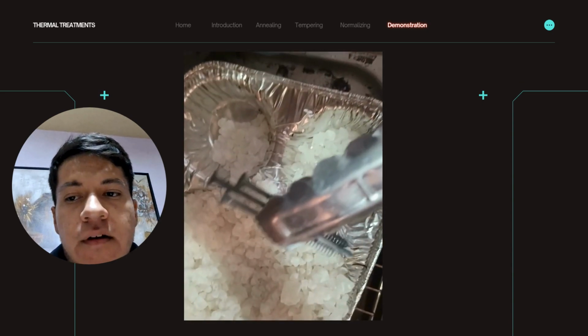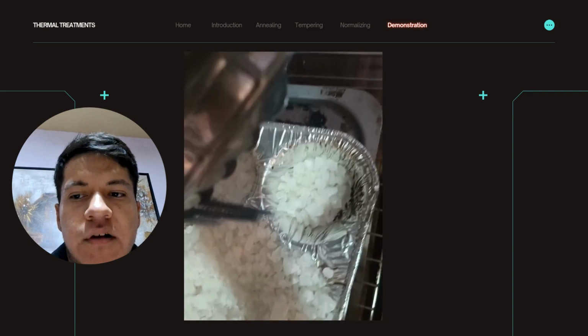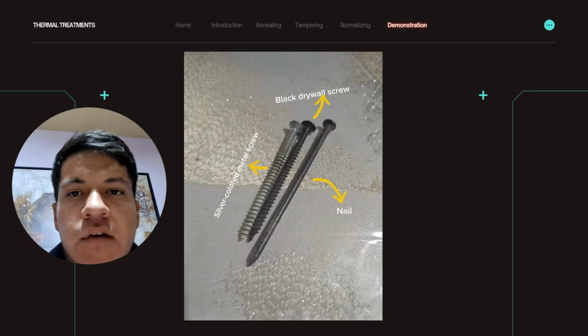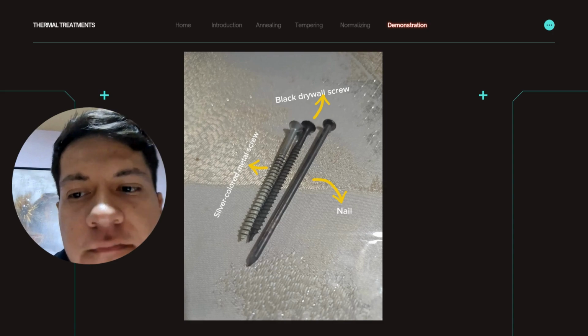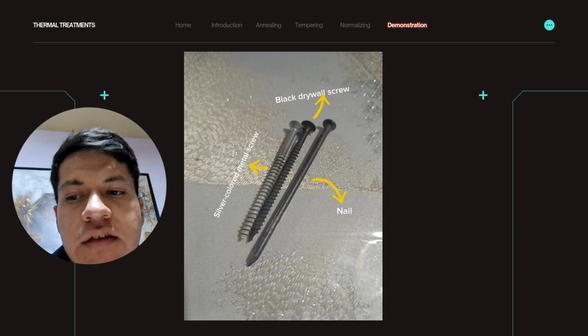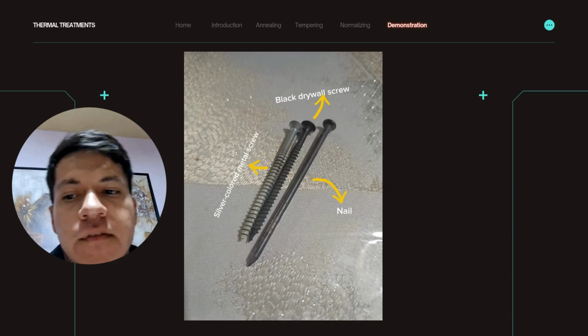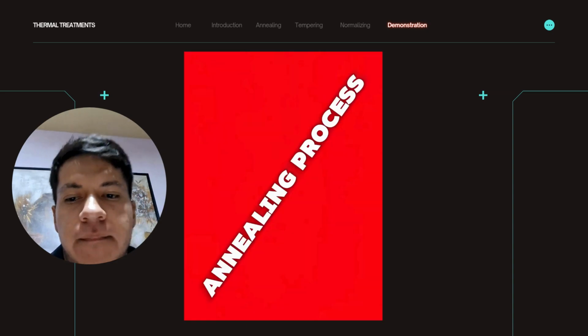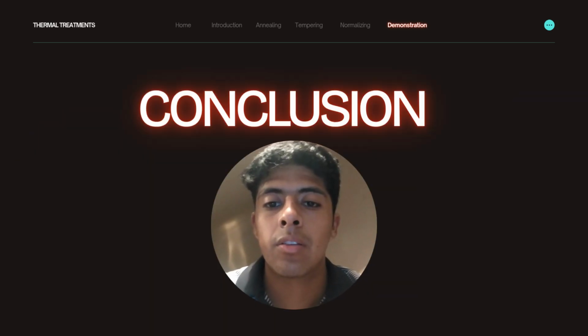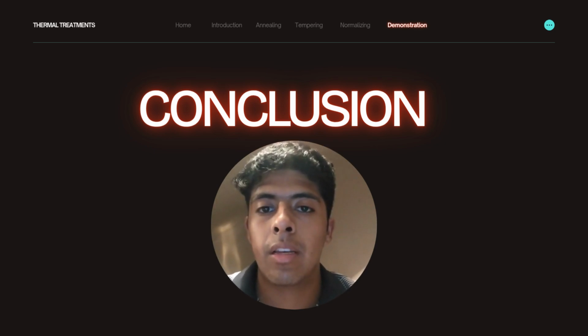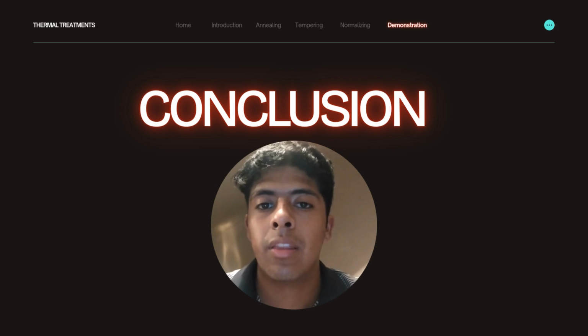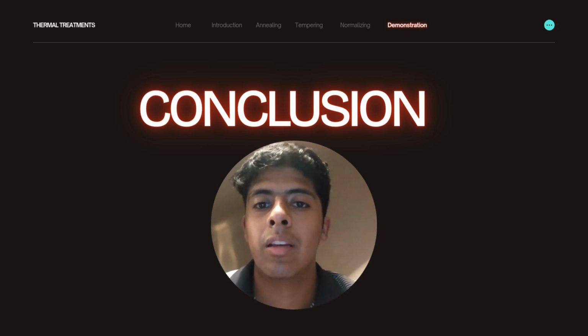This shows that even though we simulated slow cooling with hot salt, the temperature of about 250 Fahrenheit or 120 Celsius was not high enough to fully perform annealing on steel. So, our experiment helped us understand the importance of both slow cooling and reaching the correct temperature to truly change the properties of the metal.